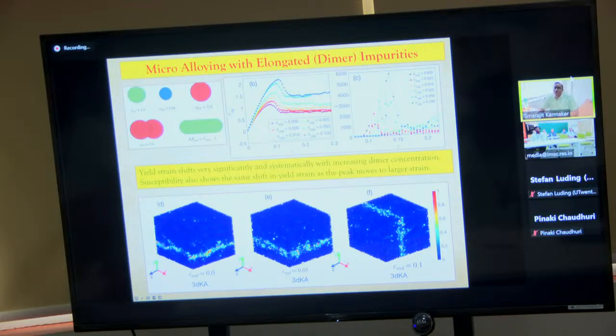And if we compute the susceptibility, it turns out the susceptibility peak increases very rapidly with increasing dimer concentration. So that is signaling some sort of shear band formation. And indeed, when we look at the spatial map in terms of this non-affine displacement, we see that already in these samples you start to have some shear band. But the major achievement in this dimer simulation was that the yield point could be shifted by a significant amount.